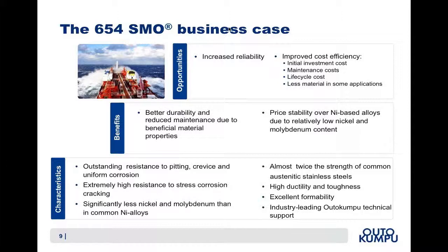And furthermore, there's better price stability over nickel-based alloys due to the relatively low nickel and molybdenum content, as we mentioned a moment ago. And as we know, it's characterized by outstanding resistance to pitting, crevice, and uniform corrosion. It has a high resistance to stress corrosion cracking, while providing almost twice the strength of common austenitic stainless steels. All this while enjoying high ductility and toughness. And underpinning all of these aspects is the superior knowledge and support you can expect from Outokumpu applied to your unique requirements.